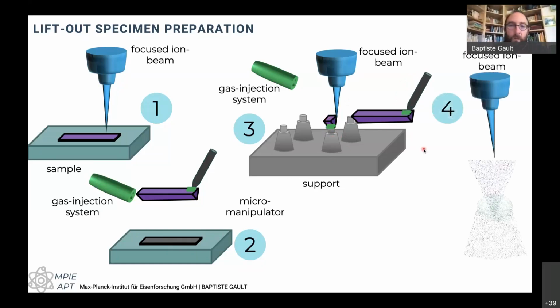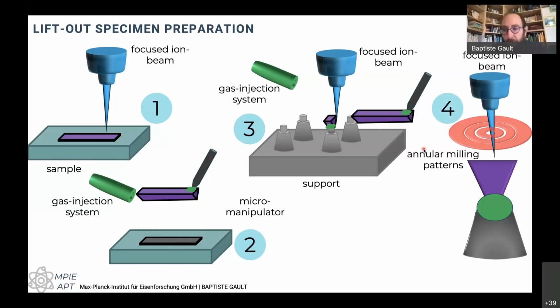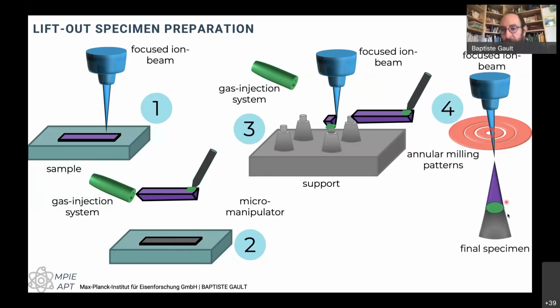And then that small piece of material we turn into a needle by using a series of annular milling patterns to go from this chunk into this sharp needle. So the interest here is that we can use an array of different SEM-based techniques like EBSD or ECCI, or simply backscattered electron imaging, to actually look for a feature that can be interesting, like a grain boundary or specific phase or a specific grain or a grain of a specific orientation.